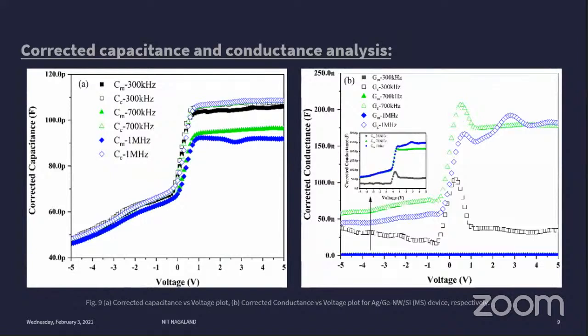We also calculated the corrected capacitance by considering the series resistance offered by the proposed structure. If we look at the graph here, we have done a series of comparisons, both in capacitance and conductance, with the measured capacitance, and we have found that while considering the effect of series resistance, there is a slight increase in the capacitance and conductance in both cases. Furthermore, we can see, our time is up.